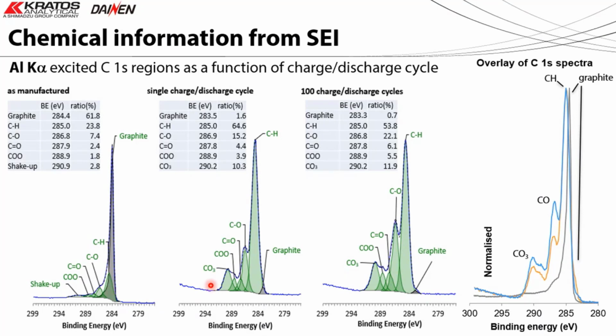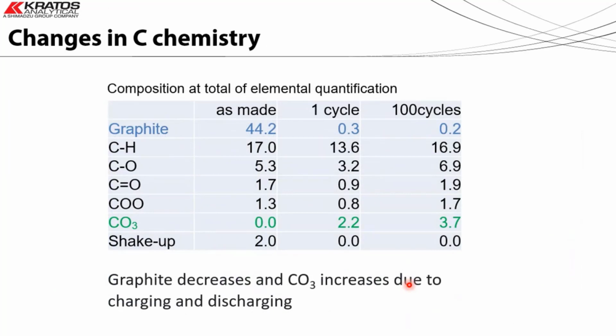And then as we increase the number of cycles, we see organic-type species in our carbon 1s spectra. And we also start to see this carbonate feature at the high binding energy. So that increases relatively as we increase the cycles. This is just the quantification of the relative area of those components.